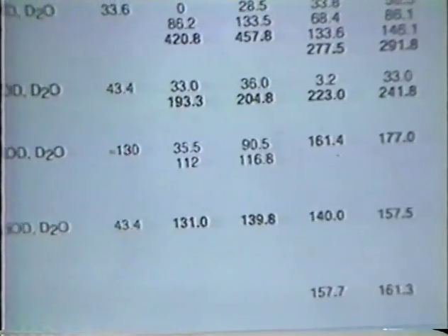As the diameter and volume, therefore, of the rods gets larger, we can place better limits on the specific neutron flux in terms of these units of neutrons per hour per cubic centimeter of palladium. In these units, the Utah results, University of Utah, would be on the order of 10 to the 8th neutrons per hour per cubic centimeter palladium.